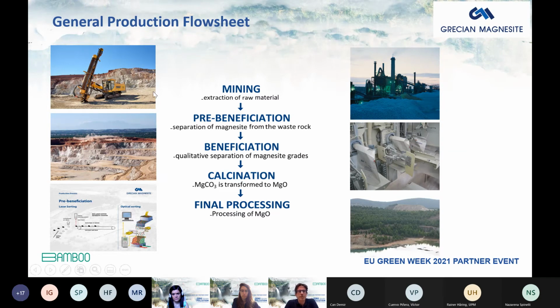We have the mine, which in Gerakini is an open pit mine. It's basically the host rock, which is dunite, that contains the valuable raw material, which is magnesium carbonate. We have to mine it and extract the raw material, and then perform a series of comprehensive pre-beneficiation and beneficiation steps to reach magnesium carbonate concentrate. These pre-beneficiation and beneficiation stages rely strongly on state-of-the-art laser and optical sorting, and less on heavy media separation.